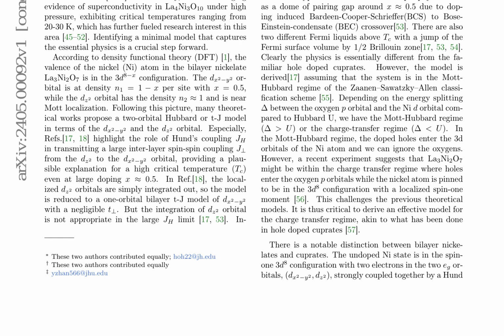The analysis is generalized to trilayer nickelates, La4Ni3O10, with the proposal of a trilayer version of the type 2 t-J model as the minimal model. Here, both d1 and d2 orbitals are assumed to be at fractional filling, with mobile carriers from both orbitals. In contrast, in the charge transfer picture, both d1 and d2 are localized, providing a spinon moment at each Ni site. The final model is one-orbital-like, similar to the bilayer case.